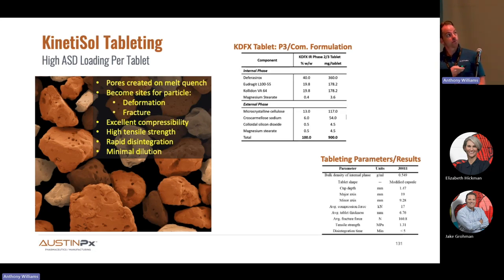And it was absolutely critical for KDFX, the deferasirox, because it's indicated for iron overload, and the doses go as high as 40 mg per kg. So pill burden is a significant issue for this therapy. Anything less than this dose wouldn't have been a viable product.